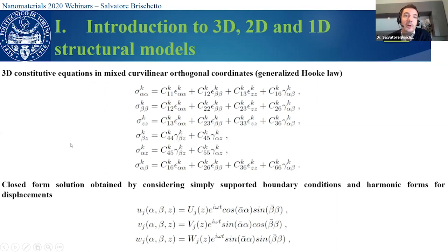And then, I recall that we want to obtain closed form solutions. In order to obtain closed form solutions, we consider harmonic forms for the free displacement components, okay? And this also means that all the edges of the structure are simply supported. And in this case, we have the index j in place of the index k only because we have divided each physical layer in several mathematical layers in order to calculate the parametric coefficients H alpha and H beta, because these equations have not constant coefficients. They have not constant coefficients because there is the dependence on z coordinate. So we eliminate this dependence on z coordinate by introducing several fixed mathematical layers.